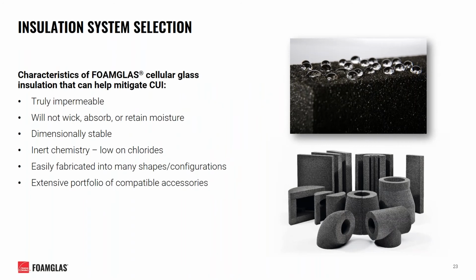So when considering these issues we just established, there are many characteristics of foam glass, cellular glass insulation that can help mitigate CUI. Starting off, cellular glass insulation is the only insulation material that's truly impermeable. Being composed of glass walls, it will not wick, absorb, or retain moisture. It's also dimensionally stable, having a coefficient of thermal expansion similar to that of steel. It's chemically inert and does not promote the corrosion of carbon steel or stress corrosion of stainless steel. It contains a low amount of leachable chloride ions and has been tested for compliance to ASTM C795, specifically for use on austenitic stainless steel.